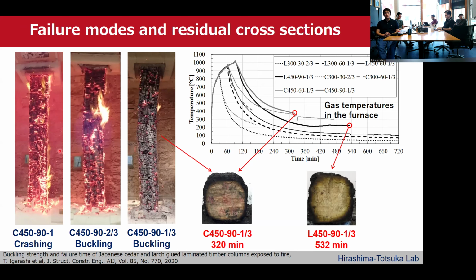On the other hand, when the load was small, the failure time was longer, resulting in buckling failure. This is because when heated for a long time, the column becomes slender and the bending rigidity of the residual cross-section decreases. This graph shows the relationship between furnace temperature and time for each test specimen.